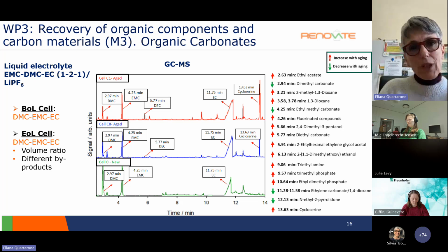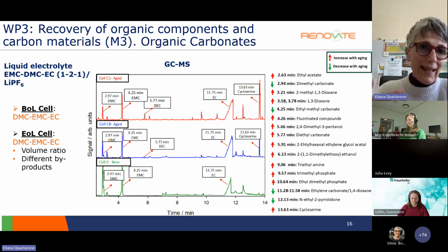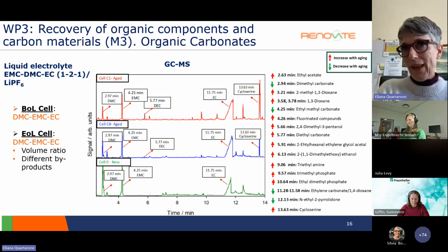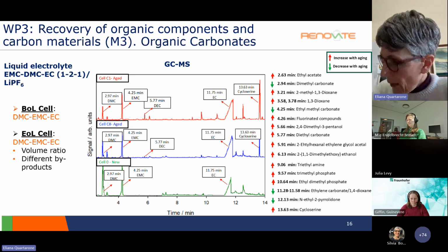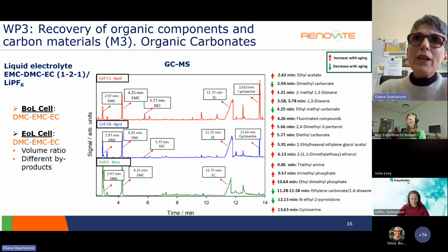And the important information here is that in case of deeply aged, end-of-life batteries, the carbonate appears really degraded with a high number of byproducts. So it's really difficult to think to recover the carbonates from end-of-life batteries and reuse them in a remanufacturing process, but we can find something to do with these low quality carbonates.